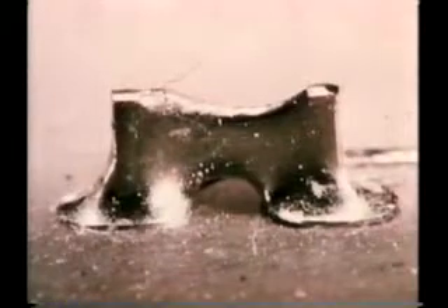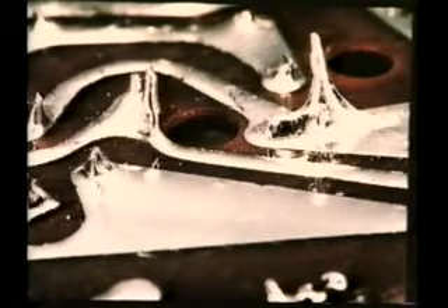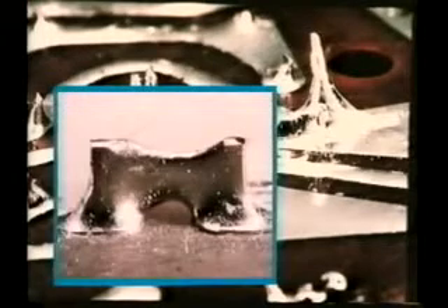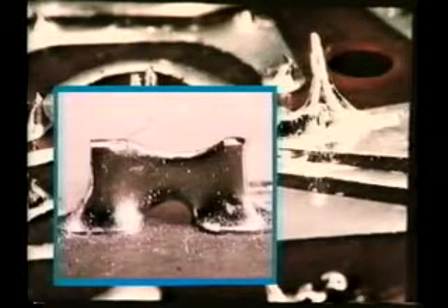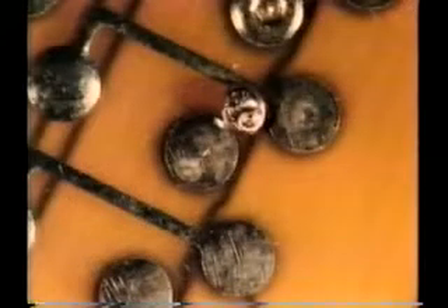This condition is called solder bridging. A bridge is an electrical path that was not intended. Here is a solder projection, also known as an icicle or a peak. These problems are typically caused by excessive solder or insufficient flux, and by the iron being too cool or being removed too quickly. These are solder balls. If one or more dislodged, they could cause a short by landing between 2 circuits. Solder balls should be removed.